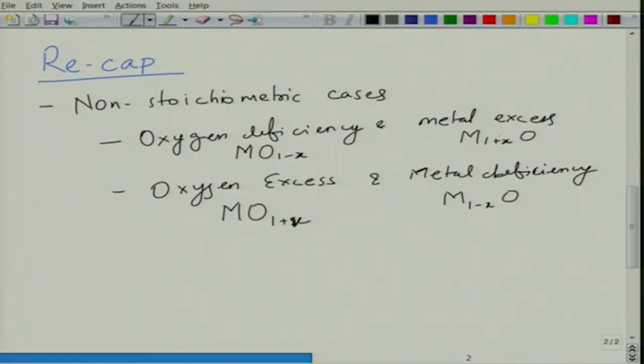In case of metal excess, you form metal interstitials, which can be again compensated by formation of electrons or reduction of metal site. Generally you do not talk about changes in the cation valences, so generally it is metal which reduces, oxidizes. And oxygen excess can be accommodated by formation of oxygen interstitials, which can be compensated by formation of either holes or metal oxidation. Okay. And metal deficiency can be accommodated by formation of metal vacancies, which are compensated by formation of holes or again oxidation of metal ions.